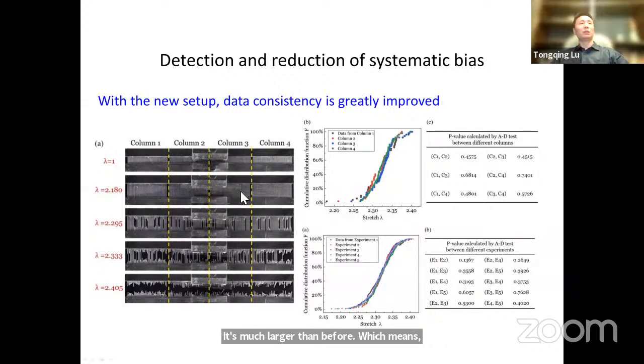each two columns have very close distributions. Also, we repeat the experiment 5 times and plot the data from the 5 experiments together, and we can calculate the closeness between the 5 experiments. Also, we get a large p value, which means with the new experimental setup, the repeatability of this setup is very good.